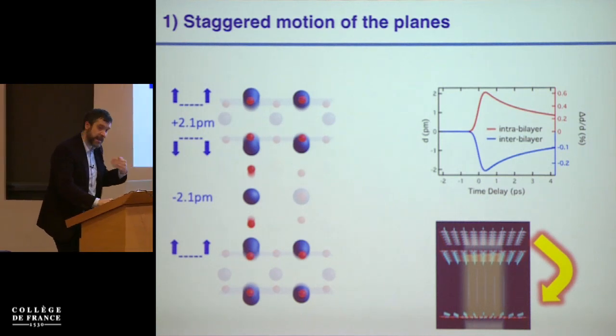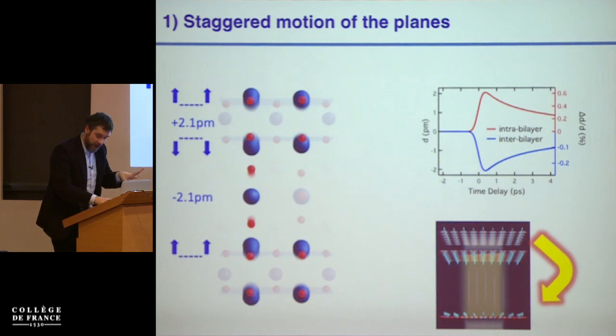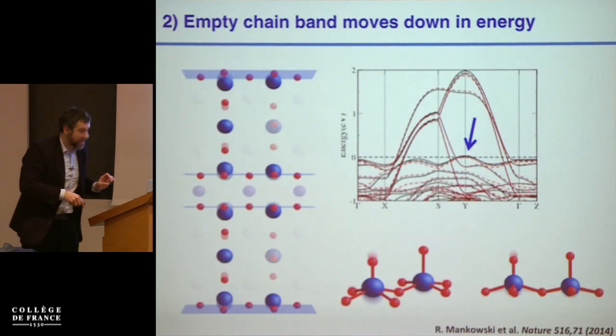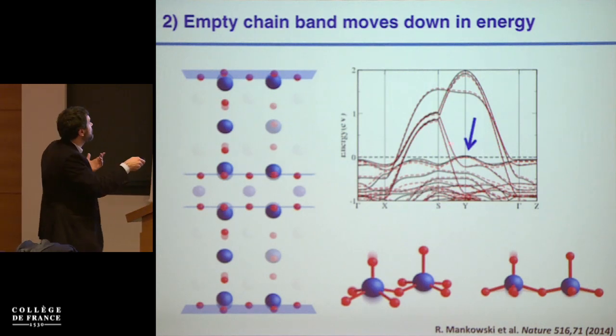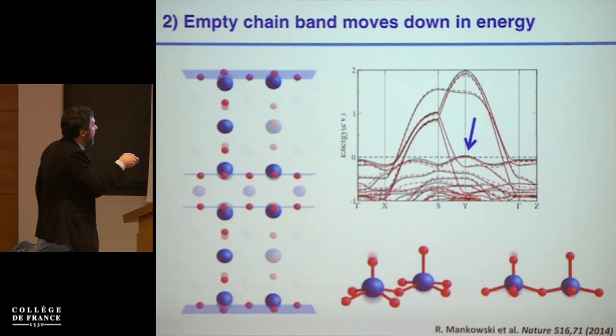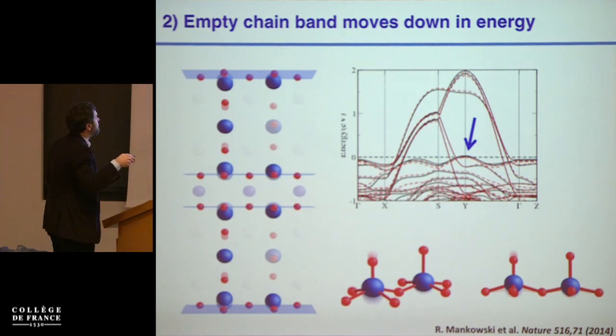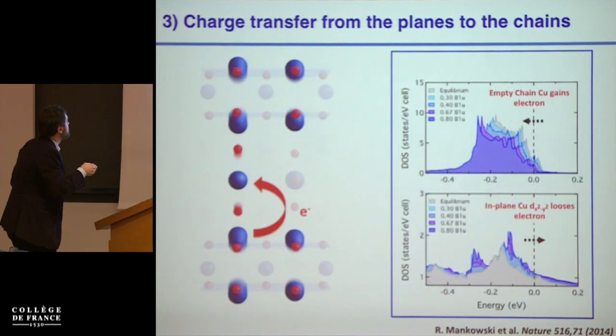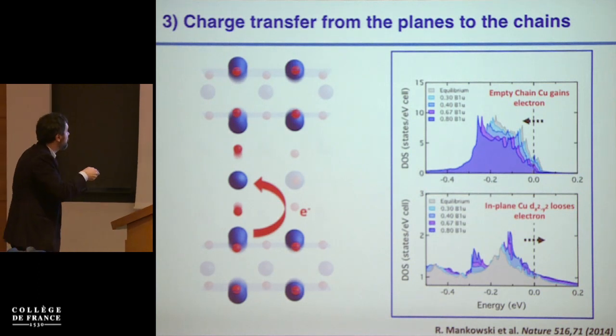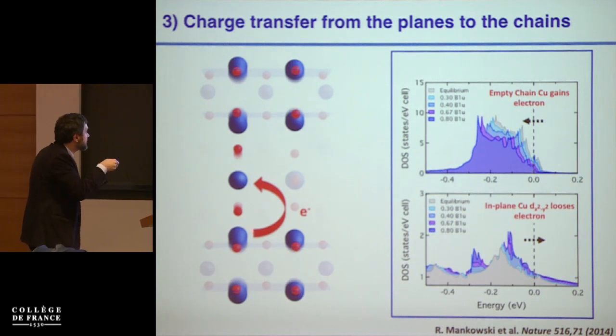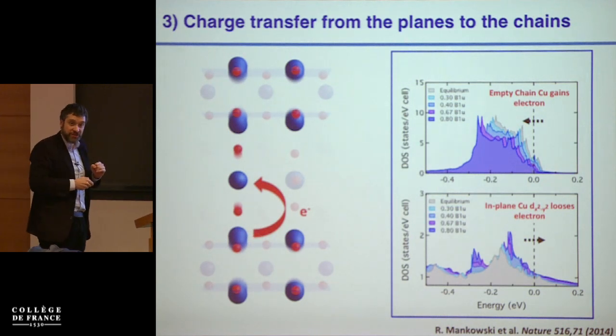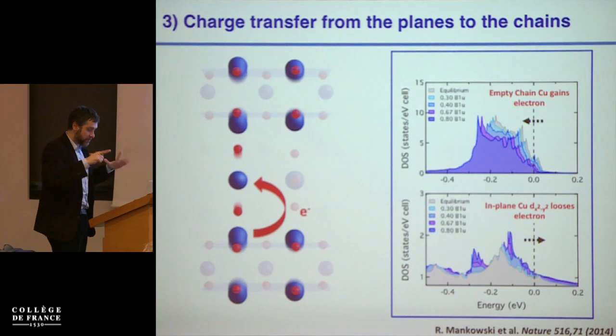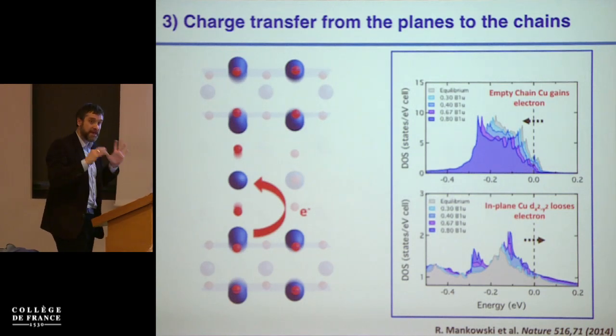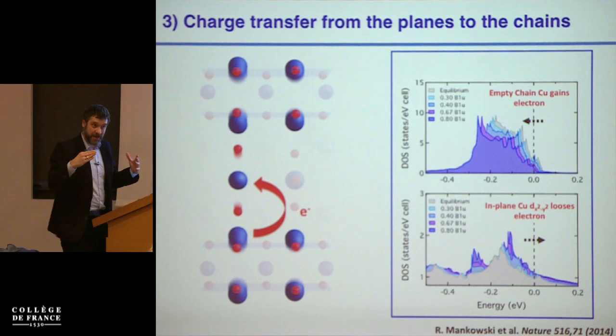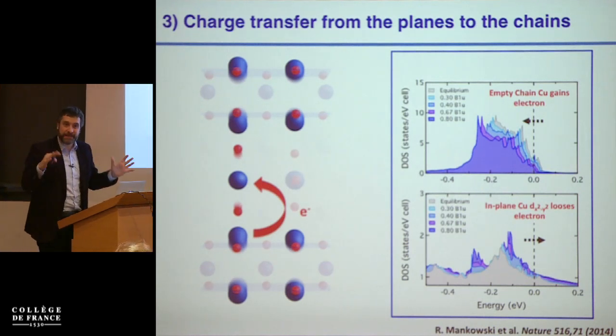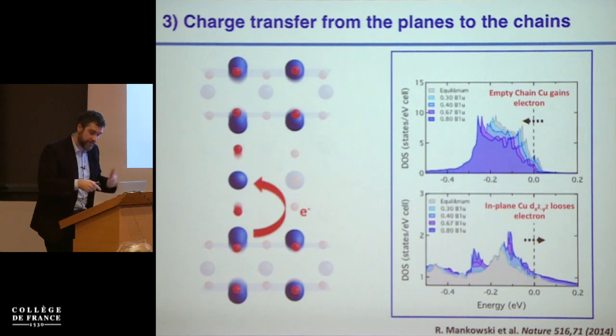And it's not really clear how finely tuned this is, but at least under our circumstances, one can do LDA calculations and measure exactly where all the bands are and convince oneself that all this would give rise to a self-hole doping of the planes due to the changes of the Fermi surface and its area. Okay, so there's at least 3 good things, unclear what is causing what, that happen along this direction that are indicative of a better superconductor.